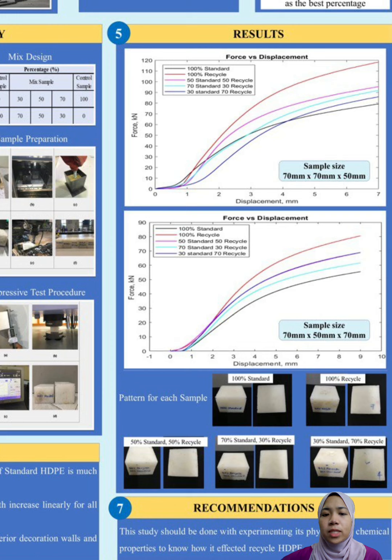the highest force obtained is 109.783 kilonewton for 100% recycled HDPE plastic, and the lowest result obtained is 79.937 kilonewton for a mix of 70% standard and 30% recycled, while for the 70 mm times 50 mm times 70 mm sample, the highest force was also obtained for 100% recycled, which is 80.48 kilonewton. So we can see that the 2 different sizes do not affect the sample strength.